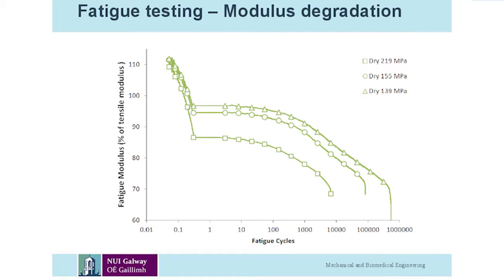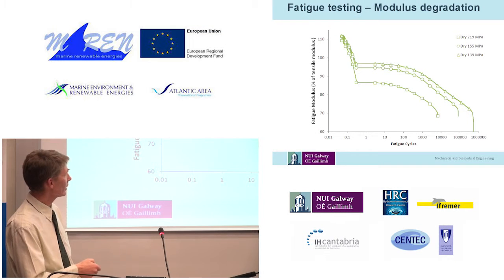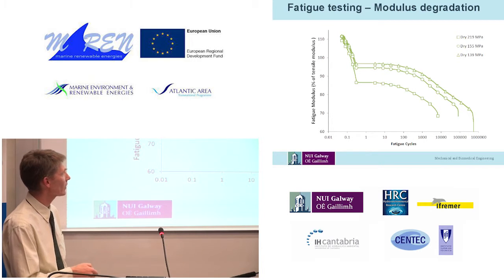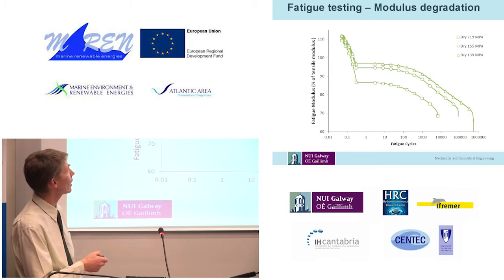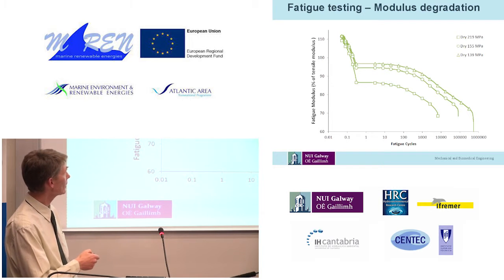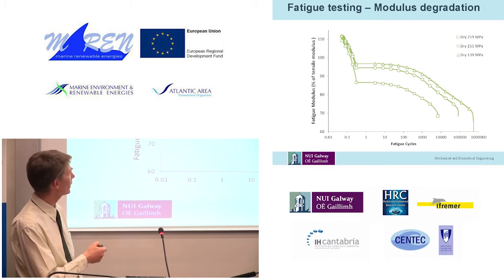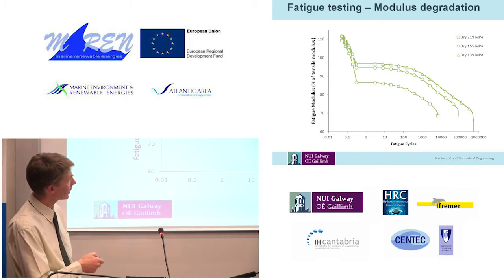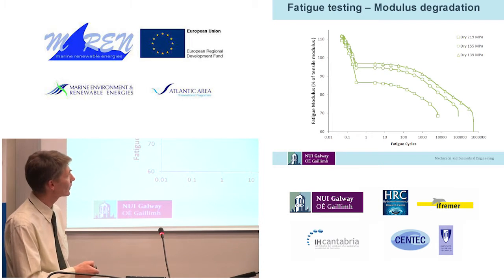When I plot all that data, and I've plotted 3 different load levels on the graph, you can see that essentially we get about a 25 to 30% stiffness loss in the material. This is actually during dry fatigue testing, and it gets to the same place by a slightly different path. The high stress material loses quite a bit at the beginning and then drops fairly steadily away till it fails. The low stress testing doesn't lose so much, but then it gets into a long period where it's steadily losing stiffness.